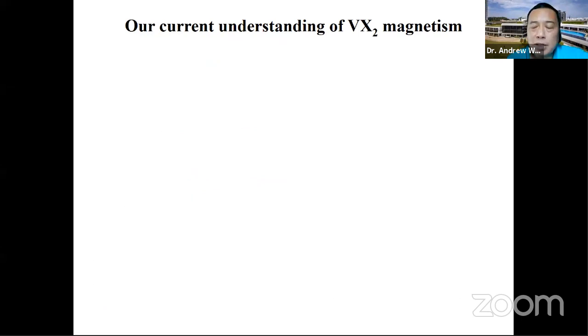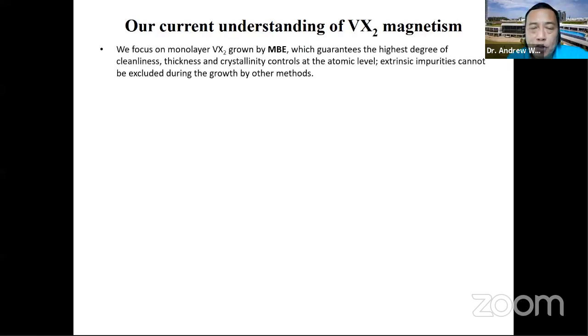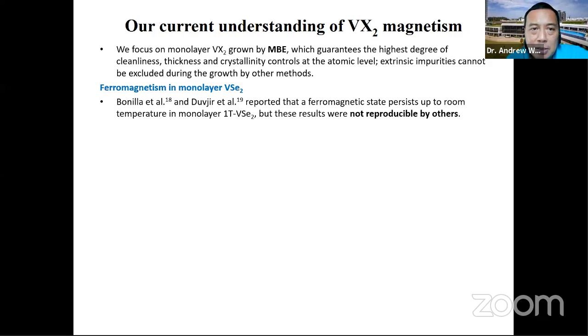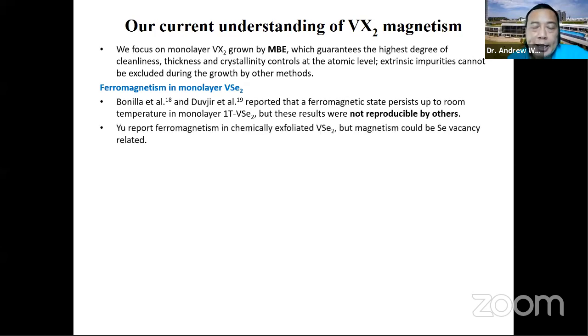So to summarize, our current understanding of vanadium diselenide magnetism is that we have grown everything by MBE, which guarantees the highest level of cleanliness. And ferromagnetism, the Betzel group reported some evidence of ferromagnetism, but these were not reproducible by others. And our colleague did a chemical exfoliation method, but the results suggest it could be related to vacancies, selenium vacancies.